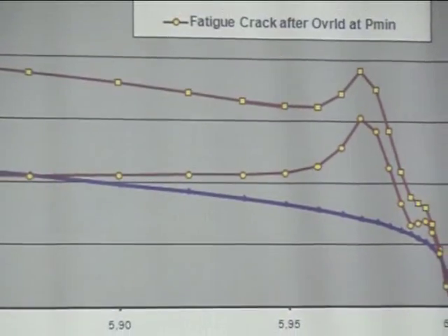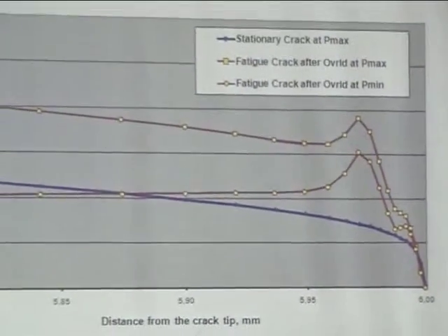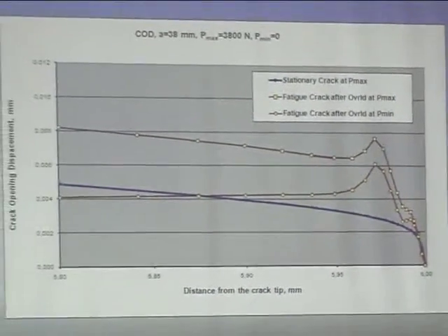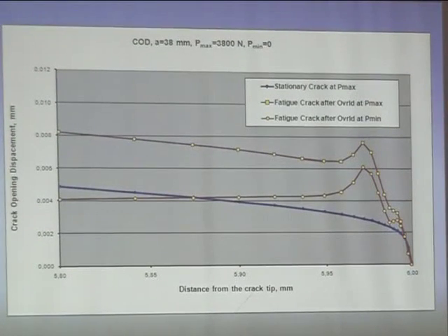And why? That was kind of a puzzle to me. And when I looked at the stress, which I will show later, there was something strange going on. The plastic zone did not deform. And the reason, which I found at the end, is that there was a huge change of triaxiality. I started with plane strain, but when I did overload, underload, there was so much triaxiality that it was almost a hydrostatic stress state. And as we know, a triaxial stress state does not allow for any plasticity. It's very hard. And that, at least from that point of view, explains the thing.